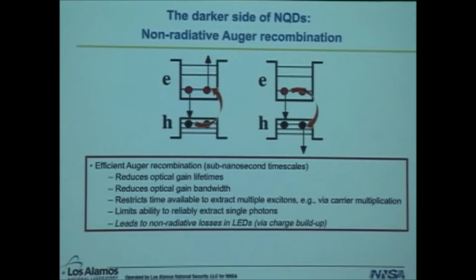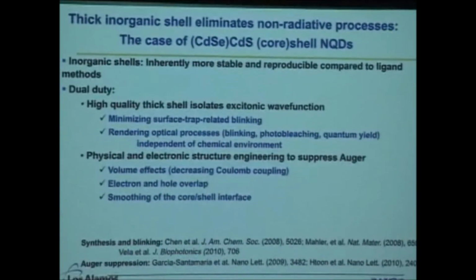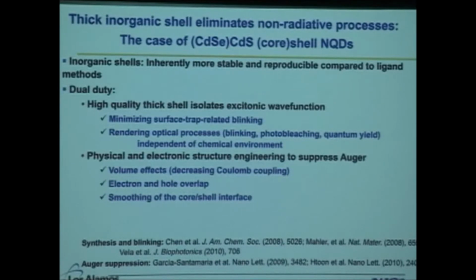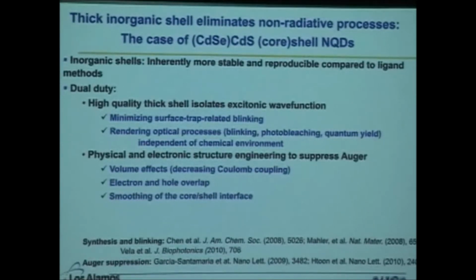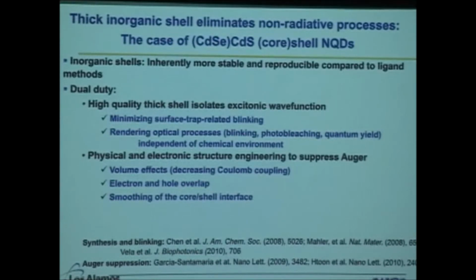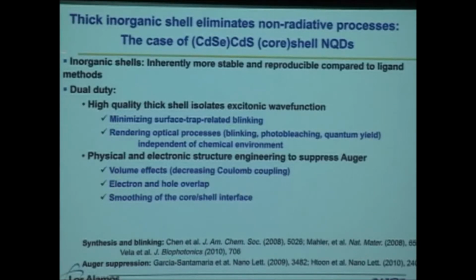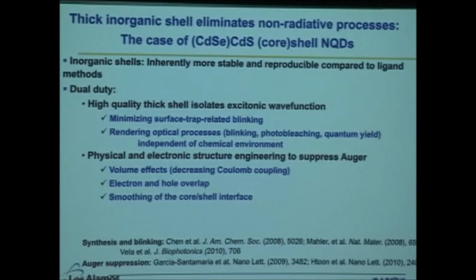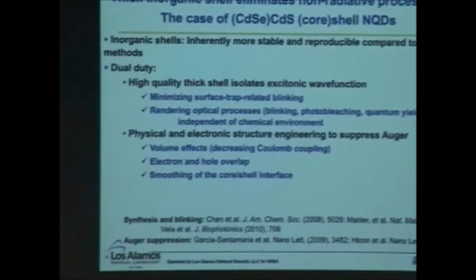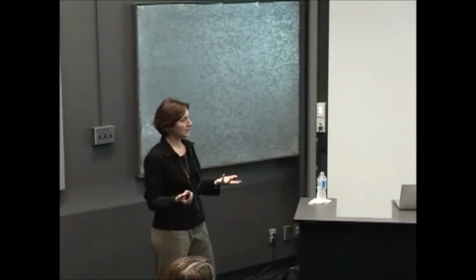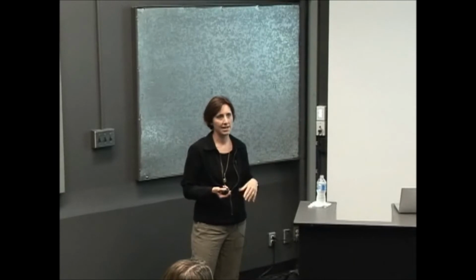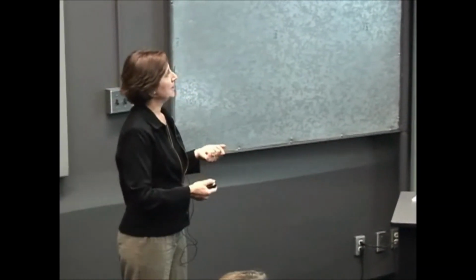And so for all of these reasons, we really wanted to find an alternative approach that would allow us to simultaneously address the simple issue of blinking as it related to surface effects, but then the more complex or interesting issue perhaps of Auger recombination, the more fundamental issue. And so we knew organic shell approaches were not adequate to the task, and so we decided to focus on inorganic shelling. It was already very well known in the quantum dot community that if you grew a thin shell of a higher band gap semiconductor onto your quantum dot, you could easily enhance the ensemble level properties. Your photoluminescence efficiencies increased. And yet, none of those systems exhibited anything different with respect to Auger, nor anything different with respect to blinking. But we thought we could tweak this a little bit and actually do a couple of things.